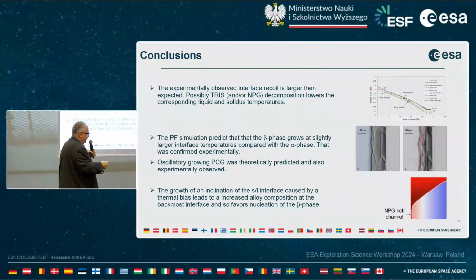So, okay, now this is more or less the important thing. We have many more details, but originally I have 50 minutes, and I calculated 20 seconds per slide. Here for this slide a little bit more. In short overview, yes, we have this recoil, which is not clear. Is it depending on the material, or is this a consequence of the peritectic coupled growth?